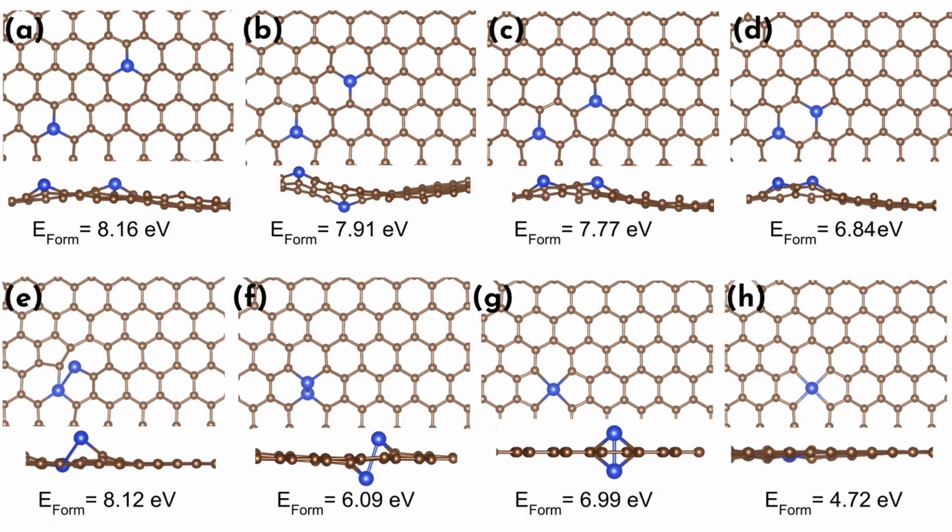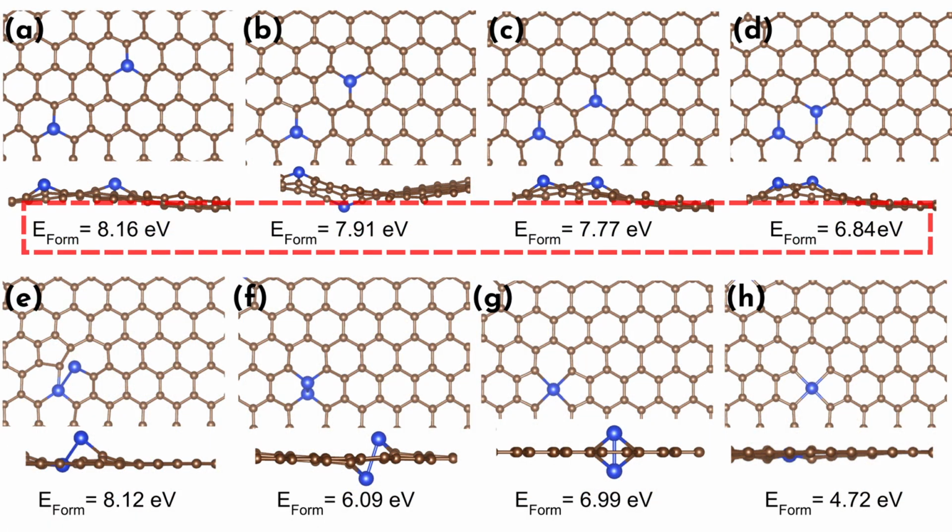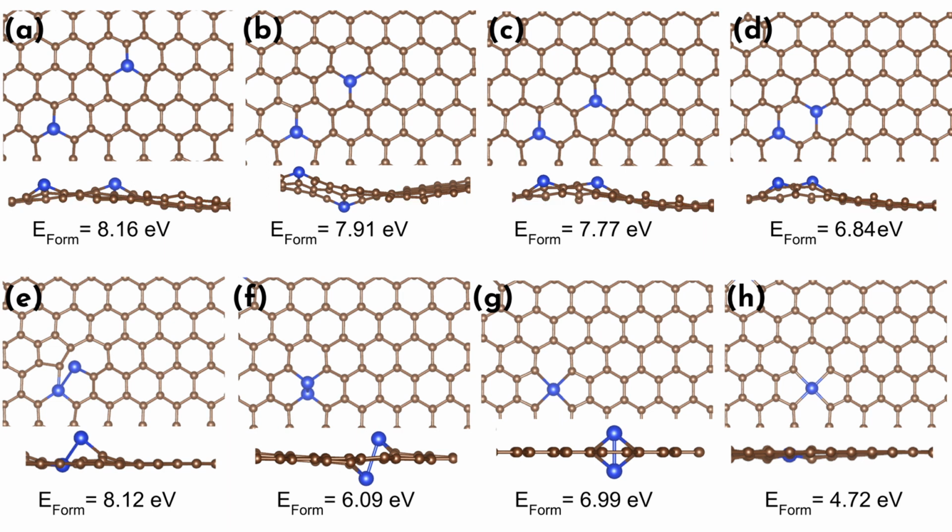Theoretical simulations from first principles reveal an energetic favorability for the agglomeration process, shown here in the decrease in energy as the atoms get closer together. The precise mechanism through which the silicon atom was lost is unknown. However, this too represents an energetically lower state than the harboring of two silicon atoms.